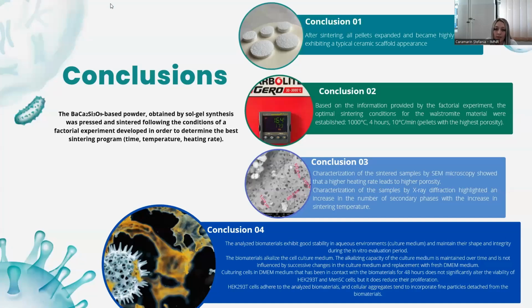As conclusions, after sintering, as you already saw, all pellets expanded and became highly porous, exhibiting a typical ceramic scaffold appearance. Based on the information provided by the factorial experiment and the analysis results, we selected as optimal sintering condition for this material the 0 point: 1000 Celsius degrees, 4 hours, and a heating rate of 10 Celsius degrees per minute.